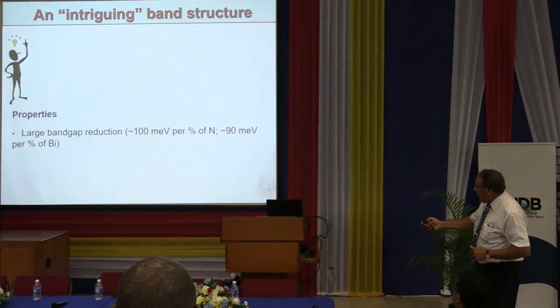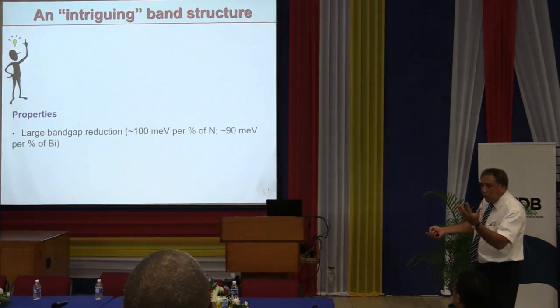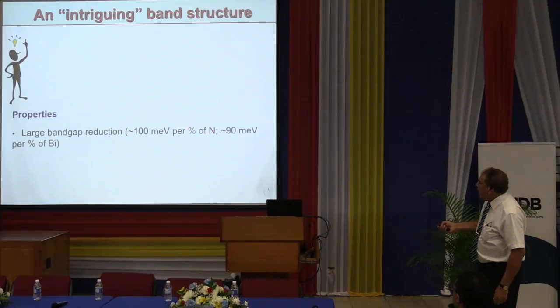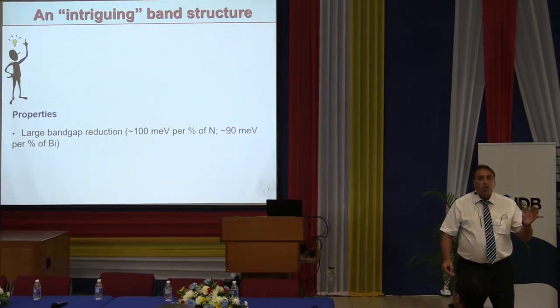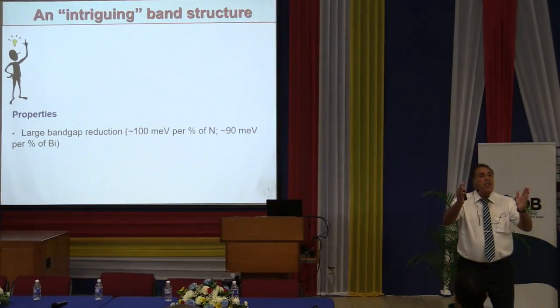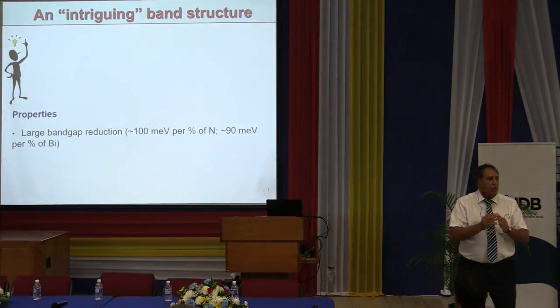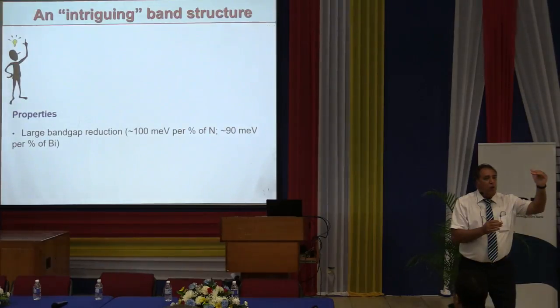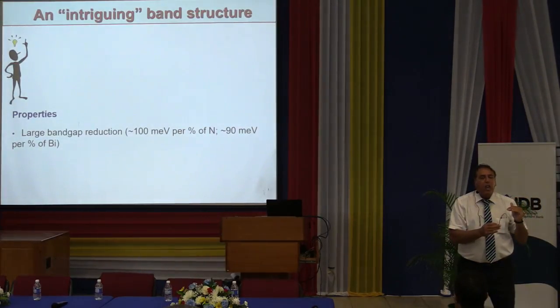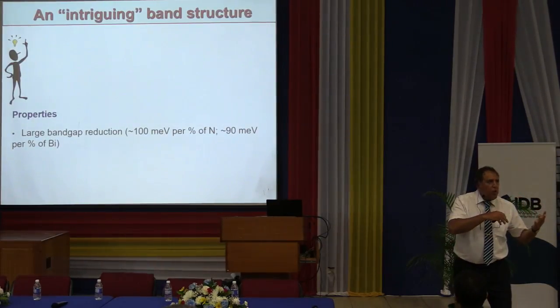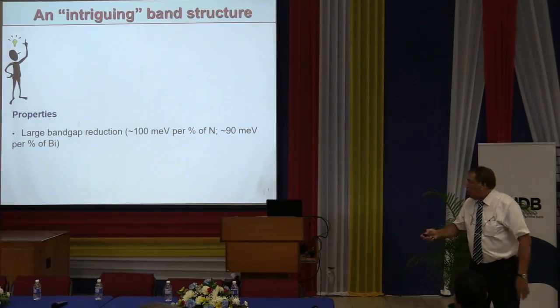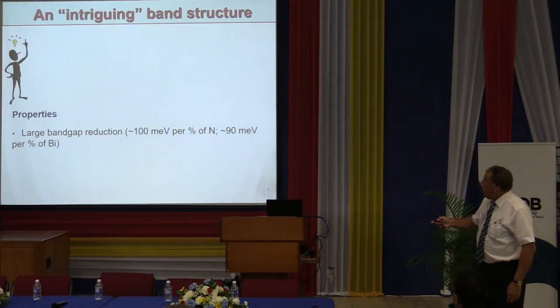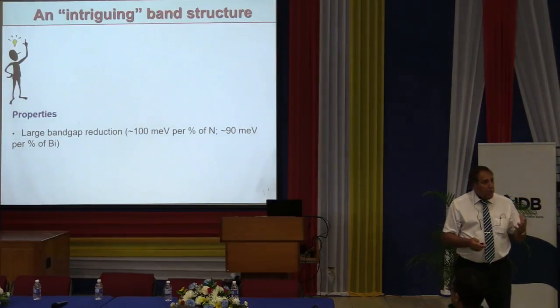So, what happens to the properties of this gallium arsenide, which was 1.4 electron volt? For every percent of nitrogen or bismuth you add, you decrease this band gap, or this energy, by 0.1 eV. So remember, I've got 1.4 eV and I want to go to 1 eV. I only need 4%, a very small amount. That's what we call dilute nitride or dilute bismuth, to reach 1 eV. And this was practically the big challenge.